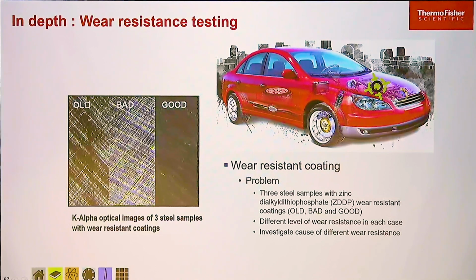Another area where we can use the imaging and also the chemical state identification is to look at surfaces through tribology samples, seeing how the layers that are applied to try and prevent wear on the surfaces change chemically through the lifetime of the part. We want to understand if you've got problems where it's not working quite as well as you'd hoped, and you're starting to see all these scratches here, whereas on the good sample it should still be nice and smooth. We try and understand the reason why that coating isn't working the way it's supposed to.